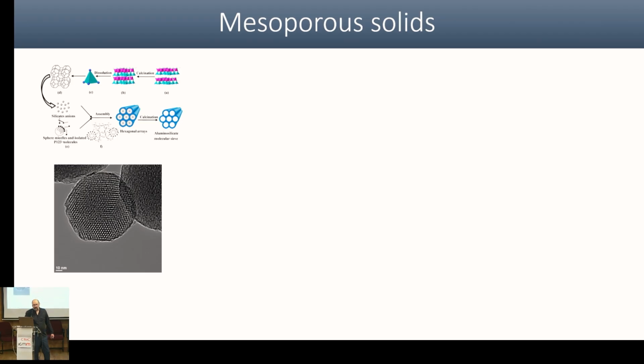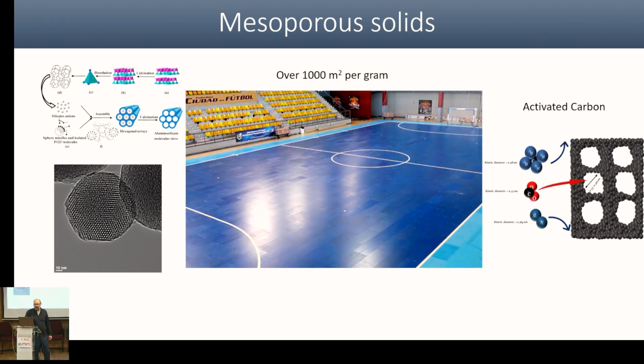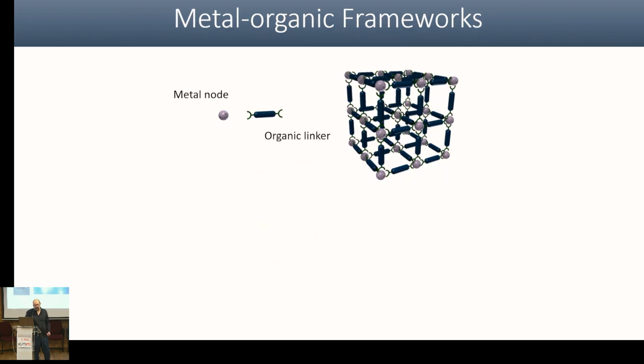Then we move to mesoporous solids and activated carbon. There's a move forward in terms of porosity. They are typically over 1,000 square meters per gram, so an indoor court for football is nice. And they are not crystalline. They have no topologies inside, so we lose one degree of freedom in that system. And in the composition, we are still attached to silica or carbon.